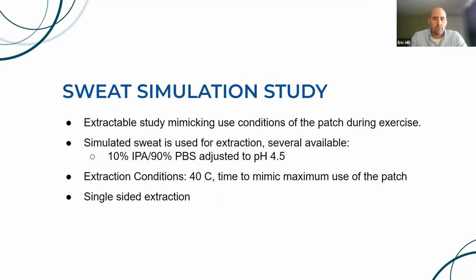Also, when an extractable study is designed, oftentimes you'll do what's called a simulation study. That's defined specifically in USP 1664. But with regards to a patch product, we're going to look at doing what's called a sweat simulation study. So here we're doing an extractable study, again, where we're extracting essentially the components of the patch. But the extractable study is very focused, and it's going to mimic the use conditions of the patch. That's going to include not only time and temperature, but also the chemistry involved. And so we're going to extract with a sweat simulating solvent. There are certainly several available in the literature. One that we've used in the past is a 10% IPA, 90% PBS buffer adjusted to pH 4.5. But again, in the literature, there are several other sweat simulating solvents that are available for use that can be documented.